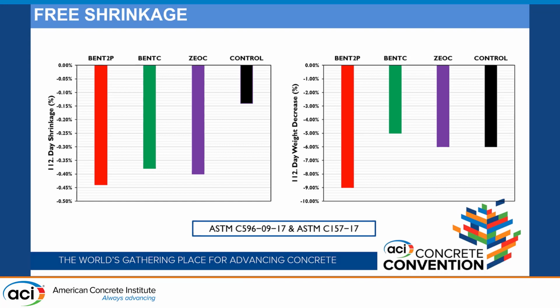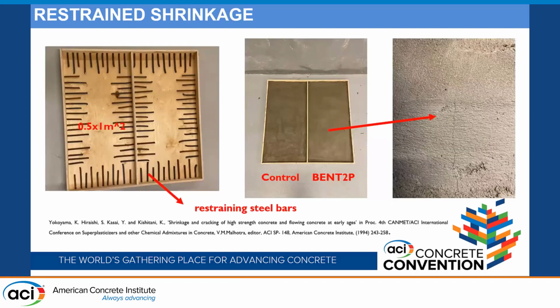So we decided to increase the scale of the samples, and we restrained the samples with steel bars. Consistent with the free shrinkage results, we first observed microcracks in the samples including bentonite and bacteria, and we started curing by spraying the samples with the nutrient medium solution, and it is still continuing.